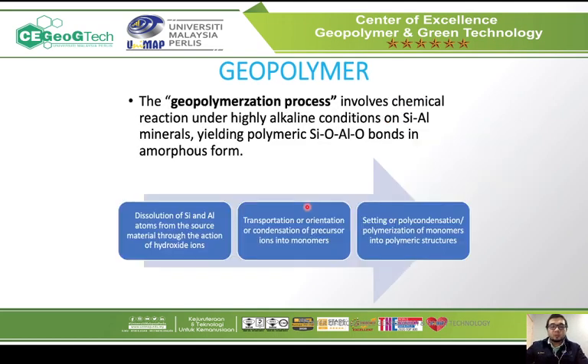The geopolymerization process involves a chemical reaction under highly alkaline conditions on silica-aluminium minerals, yielding polymeric Si-O-Al-O bonds in amorphous form. The polymerization process firstly is the dissolution of silica and alumina atoms from the source material through the action of hydroxide ions, and then the transportation, orientation or condensation of precursor ions into monomers, which are single monomers. And then the last step is setting or polycondensation, the polymerization of monomers into a polymeric structure.